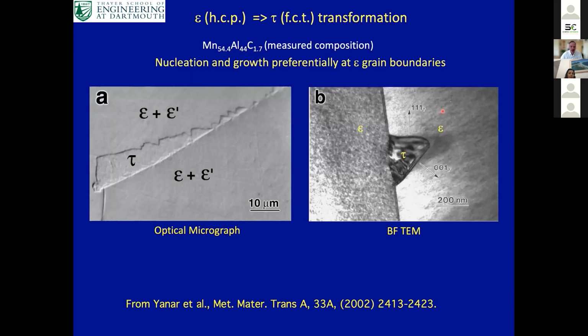Here's some images showing this transformation. The left is an optical micrograph. The one on the right is a transmission electron micrograph. And in both cases, you can see that the tau phase actually transforms from the grain boundaries. So it nucleates from the grain boundaries and grows out in particular directions into the matrix material.